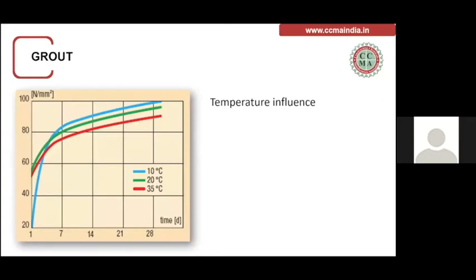Another important aspect is the temperature influence, because this is also an important parameter during grouting. Usually we suggest that grouting should be done when the temperature is low, either in the morning hours or in the evening time, especially during hot weather conditions. If the temperature is high, like 35 degrees or so, the initial strength gain would be high, but the final strength gain would be relatively low. So the ideal condition is to keep the temperature as low as possible, so that the strength achieved over a period of time reaches the maximum level of the grout capacity. So temperature is one of the important aspects. The covering or curing of those joints is very, very important.